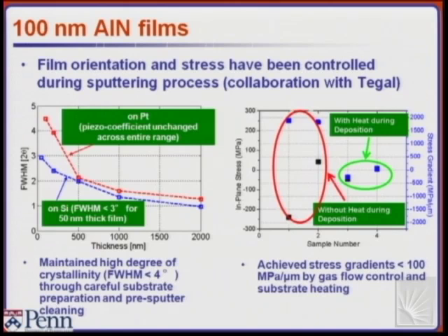And here you can see that if you do 100 nanometers, we still get on platinum, which is ultimately the material we care about, the metal electrode, rocking curves below 5. So it's promising. 100 nanometer is right here. This is actually, I think, 50 nanometers on silicon. We get a rocking curve less than 3. So we can probably stay below 3, below 5, even on platinum, and we believe we can make actually mechanical actuators. I mean, 100 nanometer is 4.5, and I'll show you now that it has exactly the same performance of a 1 micron or 2 micron thick film.